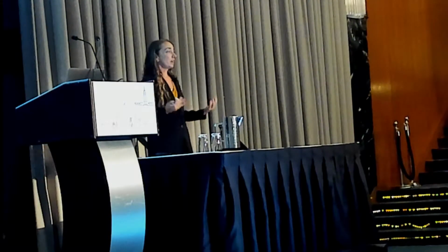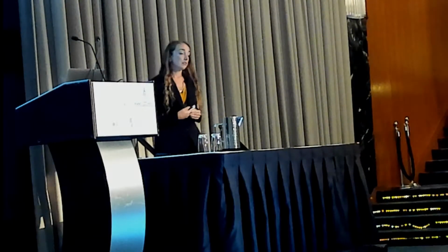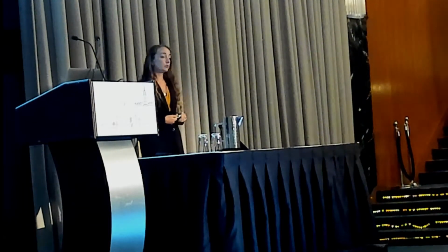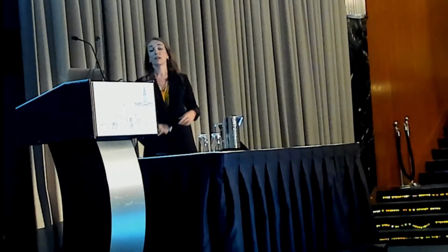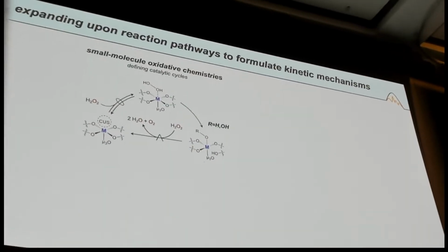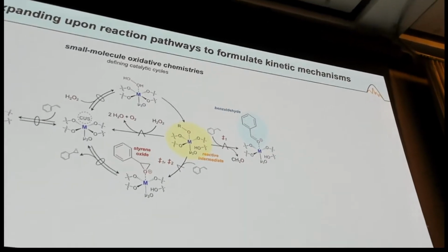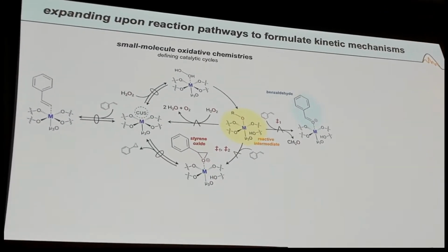So first we have to utilize our oxidant that we're feeding into the system, and that's hydrogen peroxide. So it first undergoes an adsorption onto a coordinatively unsaturated metal site. It then activates to create some surface-derived intermediate. It can undergo unwanted decomposition of hydrogen peroxide to create water and oxygen. And at higher temperatures we see a significant amount of this, with bubbling of gas through our liquid, consistent with oxygen being produced. But at lower temperatures we can actually try to trap and react this reactive intermediate.